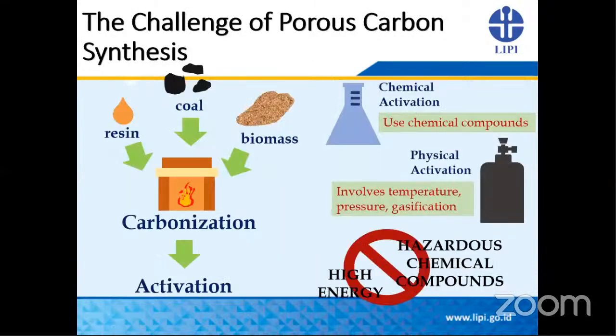So the challenge of porous carbon is that usually when we synthesize and modify it, we start with carbonization, and after that we use activation to increase the surface area and pore characteristics of the carbon. For the activation itself, it will use either chemical activation or physical activation. Chemical activation uses an abundant amount of chemical compounds, while physical activation involves higher temperature, pressure, and also gasification. The problem with these two kinds of activation is that chemical activation produces more hazardous chemical waste, and physical activation uses higher energy.